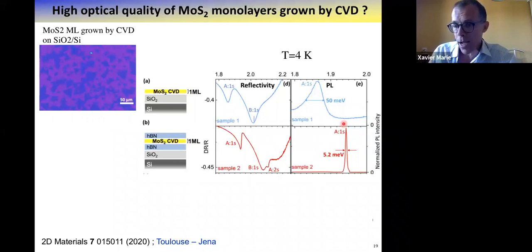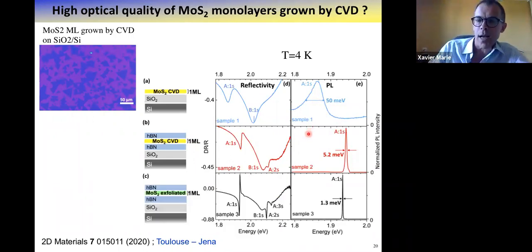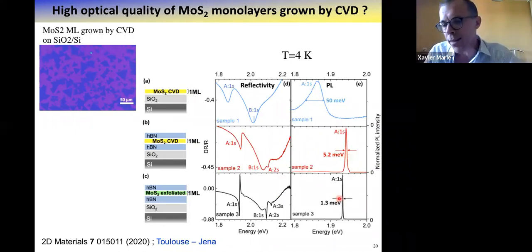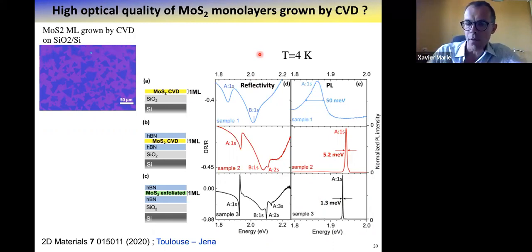This is the same monolayer. Look at the line widths of the photoluminescence. It's 5.2 millielectron volt, 50 before. So again, it's not as good as exfoliated monolayer, which is shown here, where we can go down to 1 millielectron volt or even smaller. But it clearly shows that the key point for CVD monolayers is again the control of the dielectric environment.